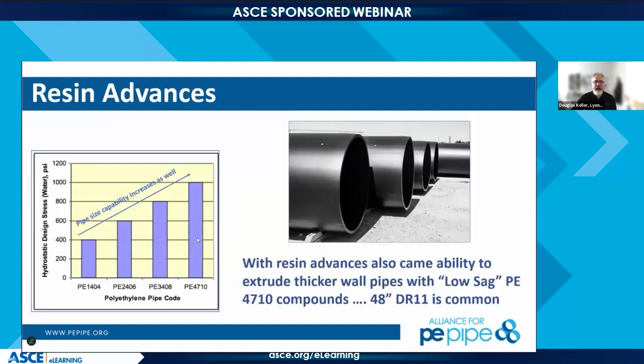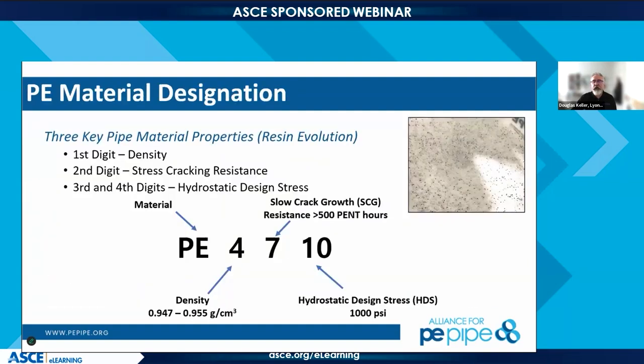Well, actually, one last thing on that slide. Up in the upper right-hand corner, you're going to see what looks kind of like little chocolate chips in the natural material. Most resin produced in the United States is natural material. We then add a carbon black master batch. That carbon black master batch gives you UV stability. So that's why we show this mix. Essentially, Richard is going to take my material, mix it with a carbon black master batch, and extrude black pipe. So I just wanted to point that out.